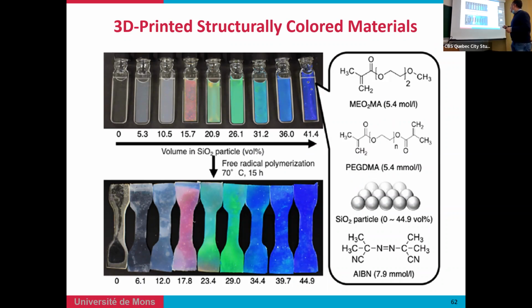We have to use a certain size of particle, in this case silica nanoparticles, having a dimension that can interact with the visible wavelength. Based on that, you can have some diffraction of a certain portion of your visible wavelength, modifying the color of your system. This is shown here in a solution containing this gel before polymerization. You start from 0% to 41% of silica, and you can see that based on the increase of the concentration of silica, the color changes.